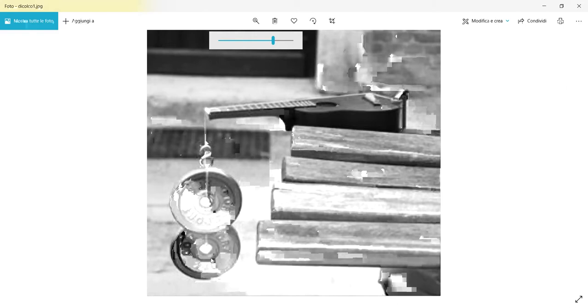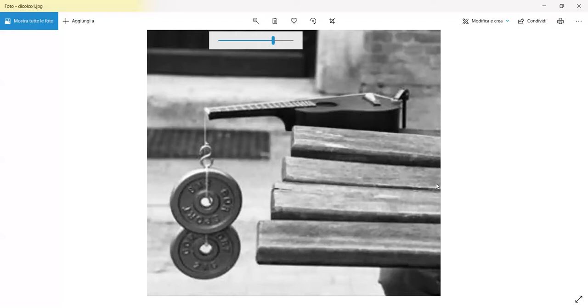I installed two strings of different diameter in order to produce by calculation a full octave, 1.2 millimeter and 0.60 millimeter. We can suppose that when I play the two strings, we have the octave. But what happens when you play the two strings is that we have an octave and one tone more. Why does this happen? Because the thinner string stretches more, dropping to 56, and due to the string formula, when the string becomes thinner, the frequency goes up.